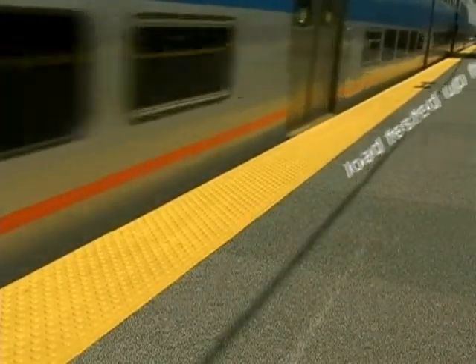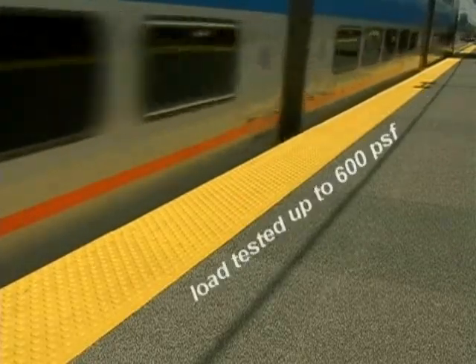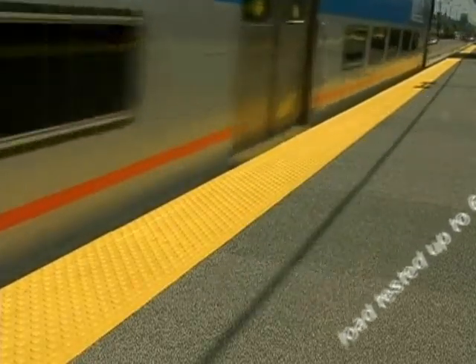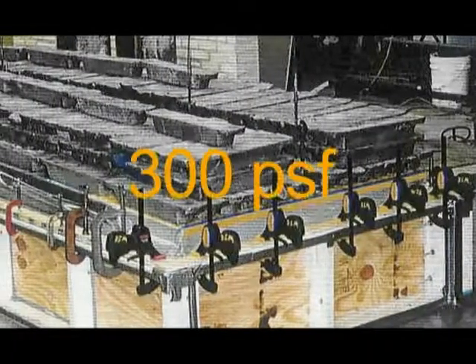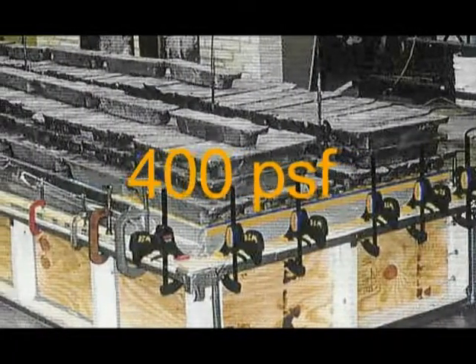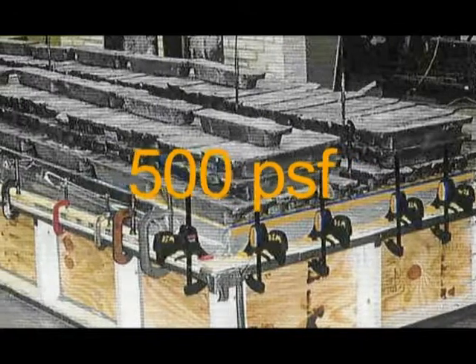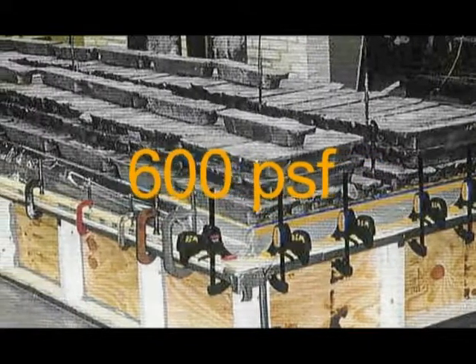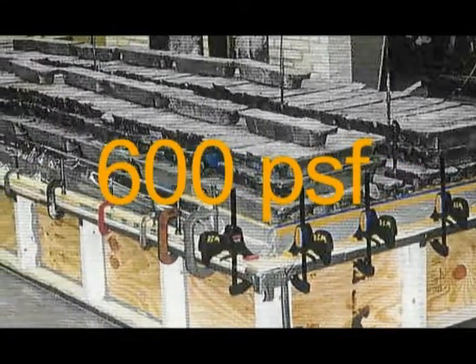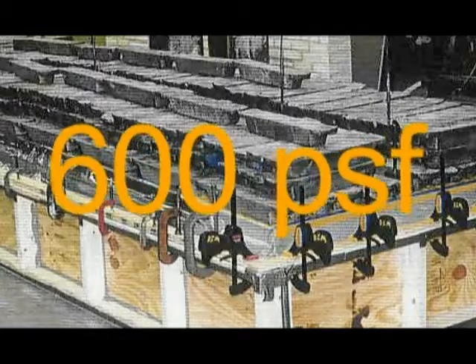The fact that we were able to load it to 600 PSF and still had no significant deformations, no failure of any element of the structure was impressive. During the course of the load test, when we applied the total of 600 pounds per square foot load to this sample that we had mounted in the lab, we held that load for 12 hours.